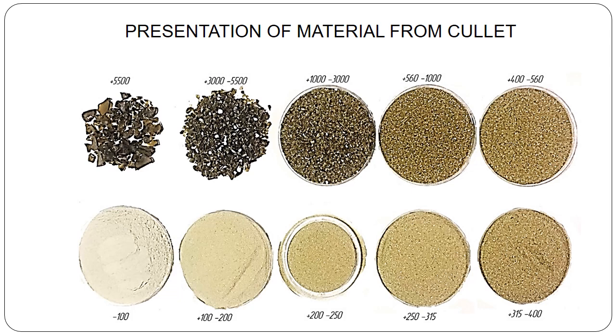All narrow classes of material size, obtained by single crushing of cullets, are used in decorative products. Powders of 100 microns are used as additives to lubricants, and as modifying additives to adhesives. All fractions less than 5 mm are used in various grades of concrete, according to the purpose of the work.